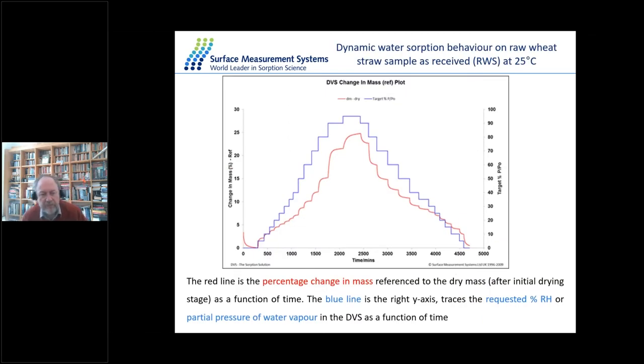So first let's look at some experimental data. And this is the behavior of some raw wheat straw samples, okay? And what you can see here, this experiment ran for about 3 days. The blue line you can see here, that's just the increases in humidity up to about 90% in this case. And the red lines relate to the mass increases. You can see this particular material took up just over 25% water at 25 degrees, okay? So, you know, it takes up quite a bit of water. So this is our as received material.